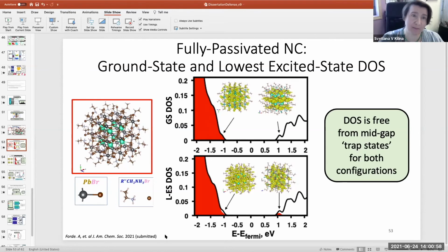Okay, but you didn't really have a comparison of this method applied to this system versus higher level methods on the same system. You just refer that this comparison was done on smaller models, and they show good agreement with the strongly confined systems. Okay. And since you were doing experiment, I thought you could directly compare the data from experiment to your computations, let's say absorption spectra. Yeah, it is possible. We did it for one of our papers, but that was with monodisperse samples. We saw a couple of peaks which looked similar in trend, but then there were additional peaks in the experiment which were off, which we think is just due to the distribution in sizes.